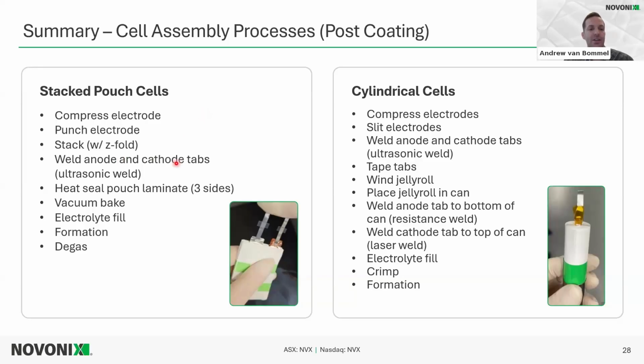Both the anode and the cathode tabs are welded ultrasonically. So the anode would be the nickel tab and the cathode the aluminum tab. And those tabs have that little piece of polymer material that will melt along while the pouch is sealing. That allows it to provide a good seal. The laminate is heat sealed on 3 sides. Since it's folded over, the 3 sides would finish the heat seal. The last side is heated and sealed with vacuum. And we do that overnight check to ensure that there's good sealing of that pouch cell.